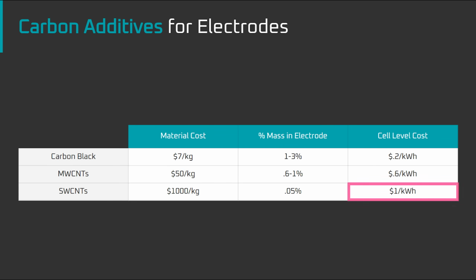Moving along, whether the application is for conventional lithium-ion battery chemistries or one that uses a high silicon loading in the anode, OCSiAl indicates that single-wall carbon nanotubes cost about $1 per kilowatt-hour. That's as compared to 20 cents for carbon black and 60 cents for multi-wall carbon nanotubes. That is, not cost prohibitive.